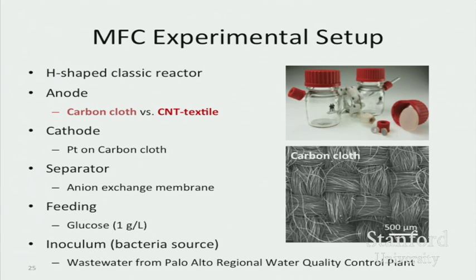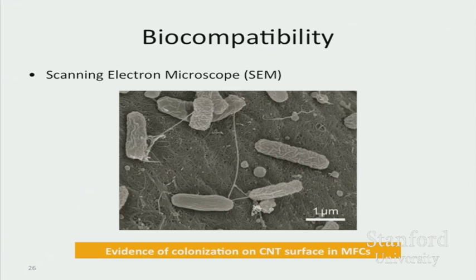And then we use this electrode to make a microbial fuel cell using this H-shaped flask right there. In the middle, we put in a membrane. You have one electrode on one side, where you can grow bacteria. The other side is your oxygen electrode, to pick up the electrons. And we compared to the state of the art at that time. That's this carbon cloth. These are carbon fibers woven into this cloth right there. That was the state of the art at that time. We want to compare our carbon nanotube textile, how well it performed versus this carbon cloth.